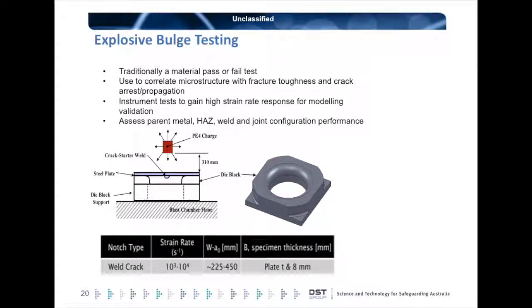For those who haven't heard this before, we're utilising what we call a standard explosive bulge test, and basically we have a big steel die block, about 750 millimetres square, and could be up to 300 or more millimetres deep. You place on top of that die block a steel plate, typical section of ship hull plating, and then above that we detonate an explosive charge at a certain standoff.